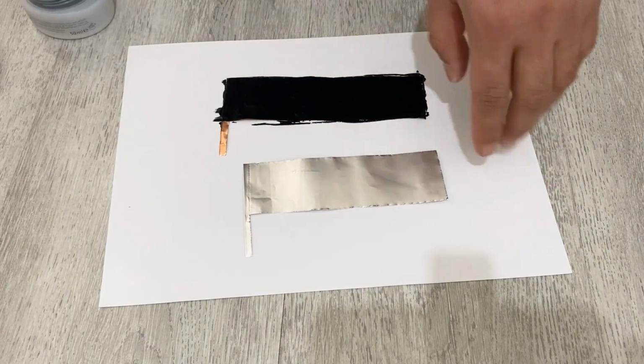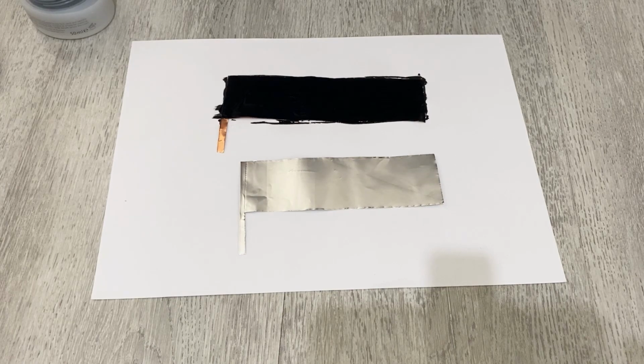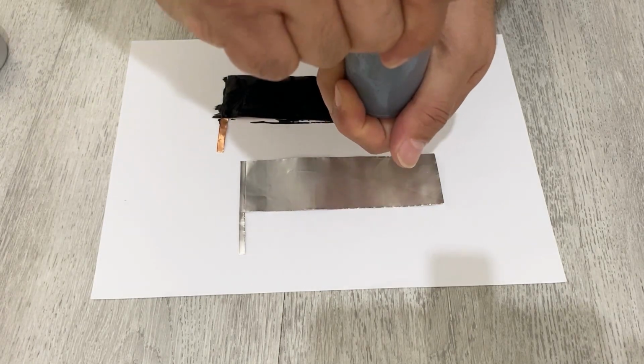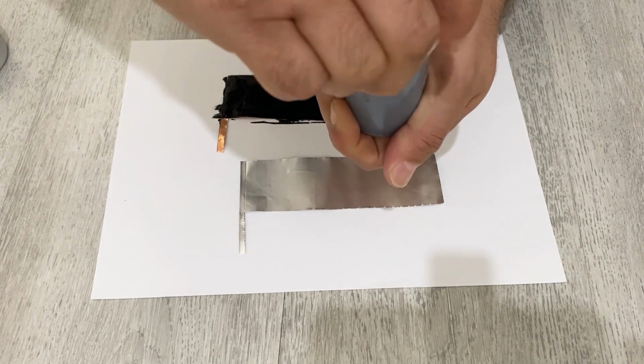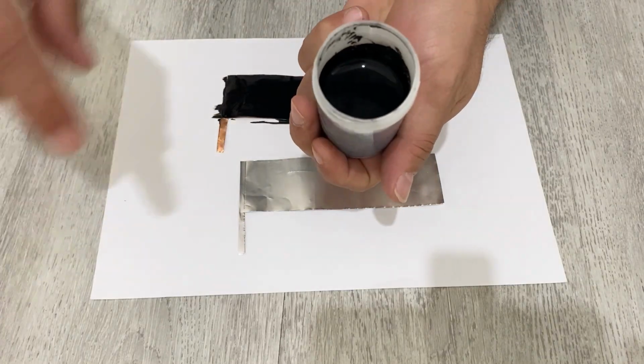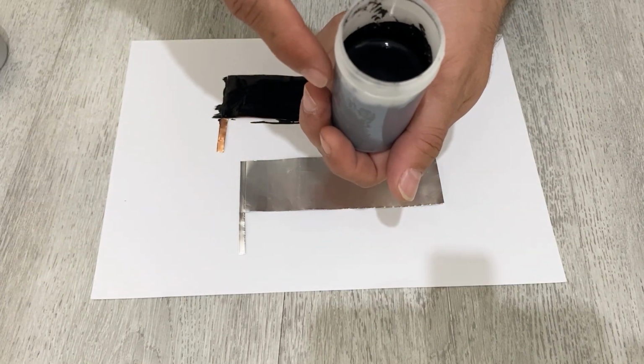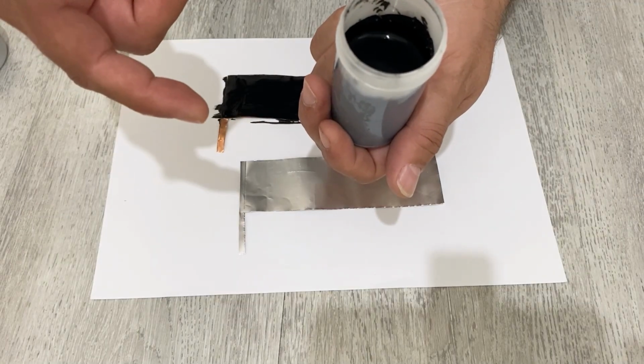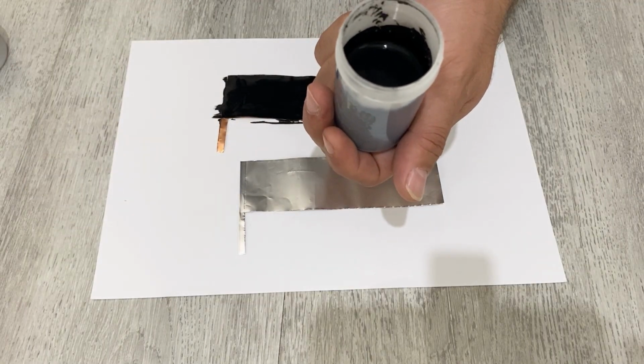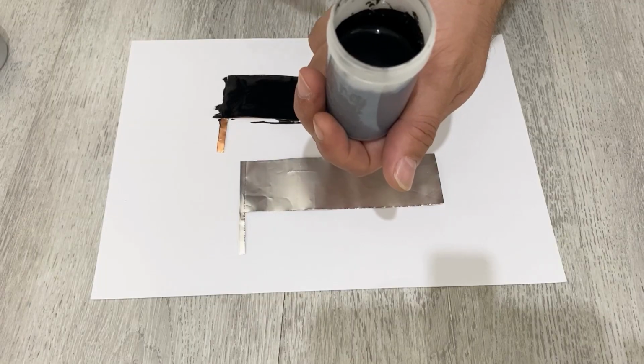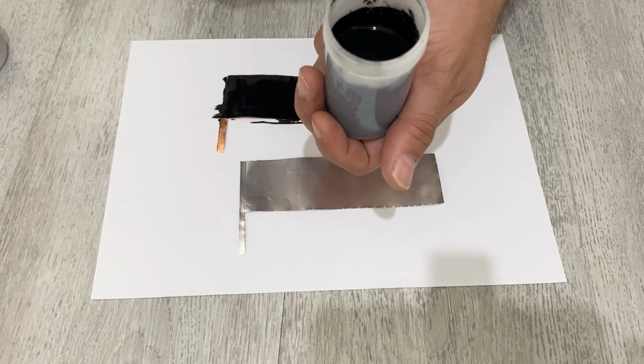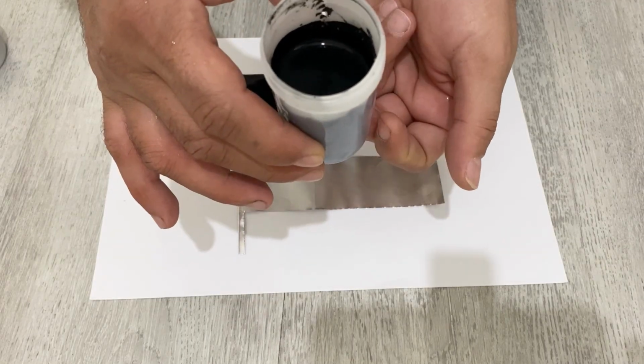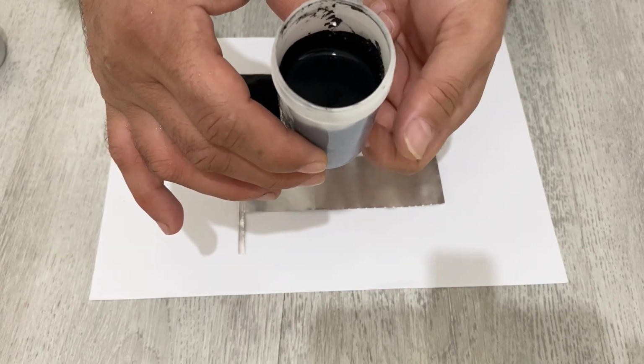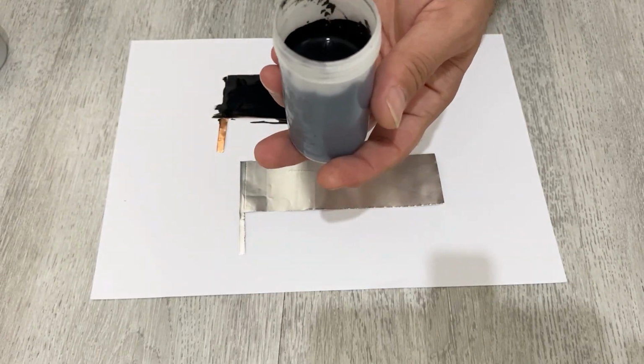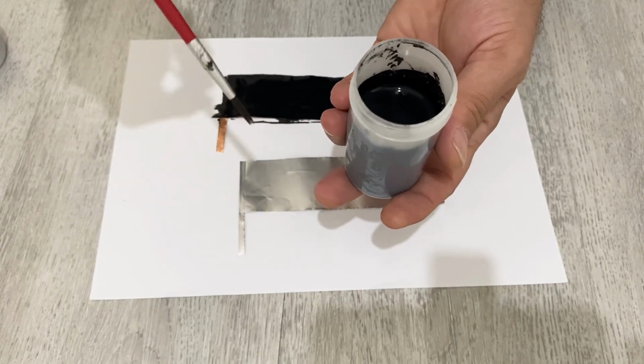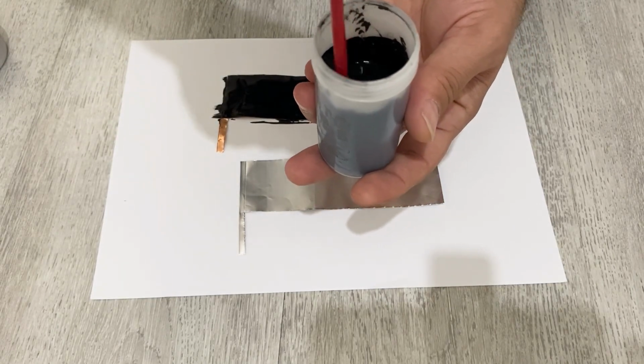Now I am going to paint my aluminum foil with lithium manganese oxide. At this time, as you see, I've just prepared my lithium manganese oxide active material. Again, to prepare this active material, you can use 20 grams of lithium manganese oxide and 2 or 3 grams of sodium silicate, and put 20 or 25 milliliters of deionized water and mix it very well until you get this slurry active material. And now I will again apply this active material on the aluminum foil as evenly as possible, just like the other one, my friends.